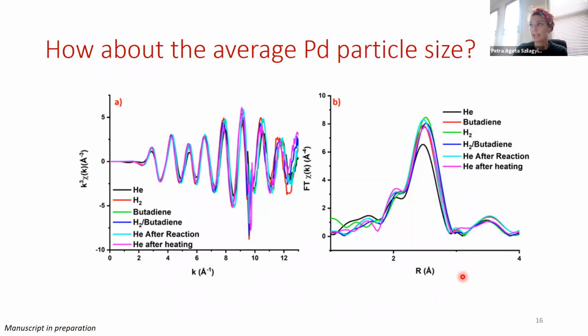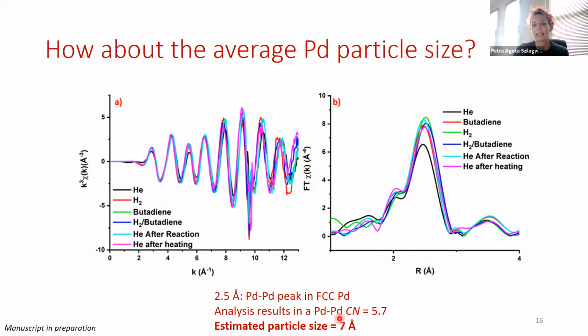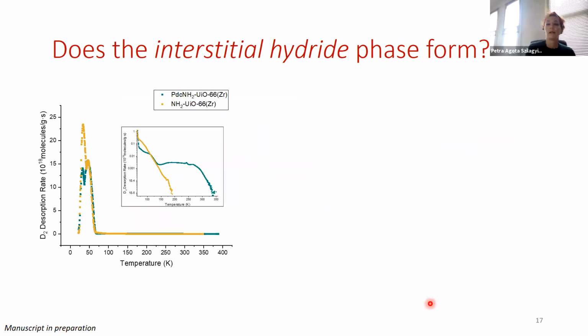From the TEM, we saw that the particles were more or less the same size as we expected, so around 7 angstroms, but we also wanted to see what the average particle size was, and that we could do with EXAFS, and indeed it could be refined that the estimated average particle size is around 7 angstrom as well. So the local and the global probes are in quite good agreement. So we know that we've got this particle, which in theory should inhibit the interstitial hydride. So then we looked at whether indeed this is true.